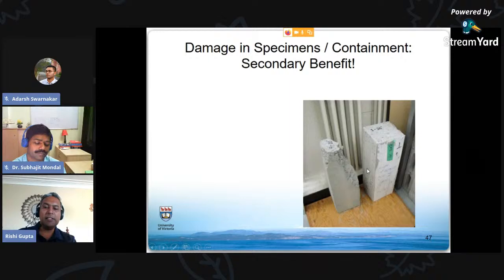graphic. So I call this secondary benefit. And these are the examples of 2 columns. So this is your traditional column, normal concrete, no PVC, no formwork, nothing. This has been tested in compression already, and you see the amount of concrete loss that has taken place, which is expected. Nothing wrong with that. The column next to it, same height, has also been tested in compression. So this has failed. If I load it again, the load capacity is not going to go up. It's going to be a very flat curve.